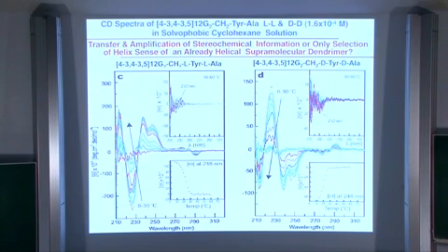You see that this ellipticity that had less than 50 units is amplified by about 5 orders of magnitude. We know that there is a transfer of stereochemical information from the dipeptide to the dendritic part of the molecule. We don't understand the mechanism. We can get a lot of information about the position in which you can place this stereochemical information and how fast and how efficient is the transfer of stereochemical information, but we don't understand the detailed mechanism.